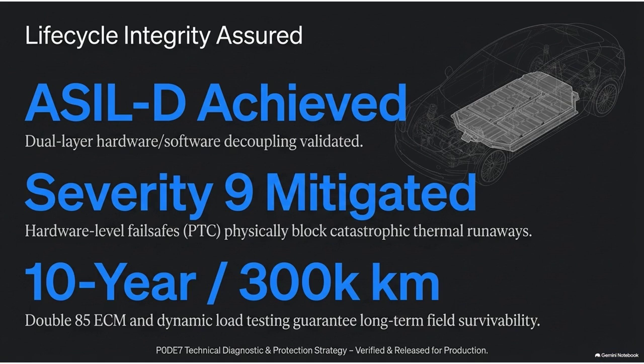And they blast it with a continuous 5-volt bias across those wet pins for 500 agonizing hours. Which mathematically equates to over a decade of real-world environmental stress. And after 500 hours, what are the survival numbers? Leakage current must stay under 1.0 milliamp. Insulation resistance must stay above 500 megaohms. And when they look at it under an electron microscope, there must be 0 microscopic metal dissolution, 0 conductive tin whiskers, 0 dendrites. Total perfection after 500 hours in a boiling swamp.